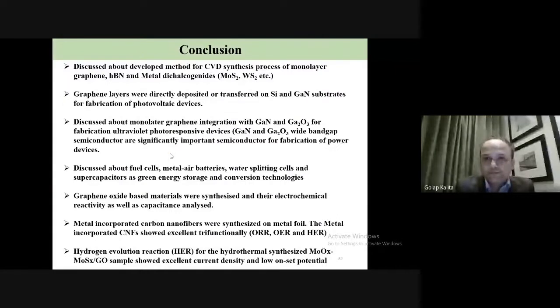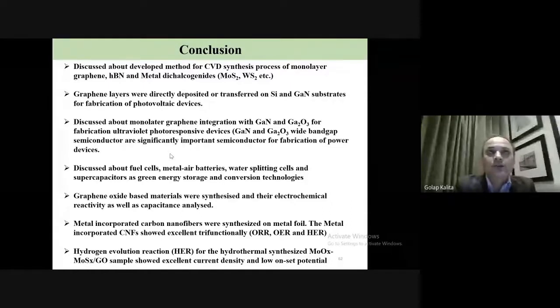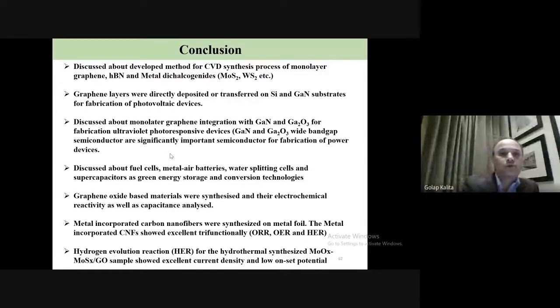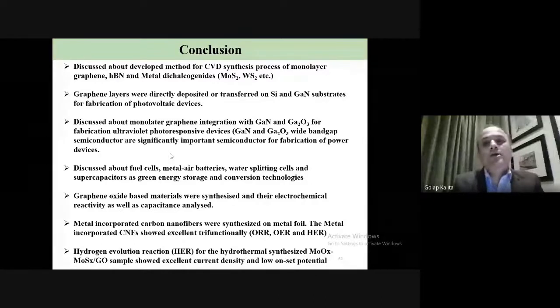Okay, this is the conclusion of my talk. I discussed the CVD process to synthesize graphene, hBN, and molybdenum disulfide. The CVD process is very interesting because you can grow very nice monolayer graphene or hBN or molybdenum disulfide on a substrate, or you can grow a uniform film, not by solution process. Maybe to grow a monolayer uniform film is very difficult by solution process. But solution process also has advantages, as I discussed.